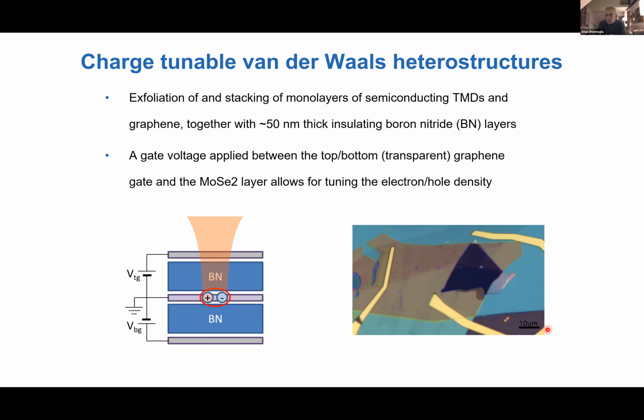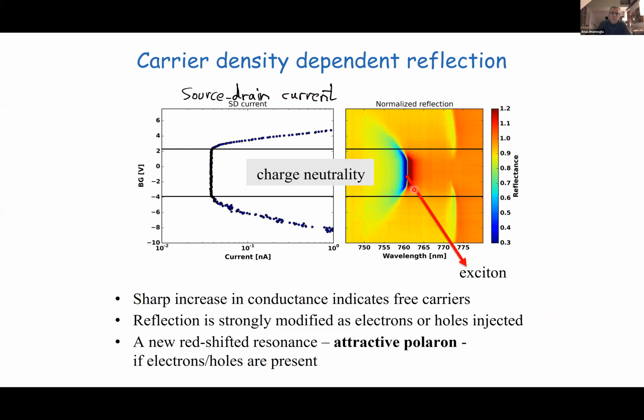Now I would like to tell you about charge tunable van der Waals heterostructures, because this is, after all, what we need for the Wigner crystals. In this case, we embed our monolayer generally between top and back gates, which are graphene layers. Through the applied voltages and the direct contact to the semiconducting layer, we can tune the electron density or the hole density in this system. This is a micrograph of a relatively simple device with a single monolayer and 2 contacts. If you have 2 contacts to the TMD, you can also drive a source drain current while controlling the electron density through the gates.